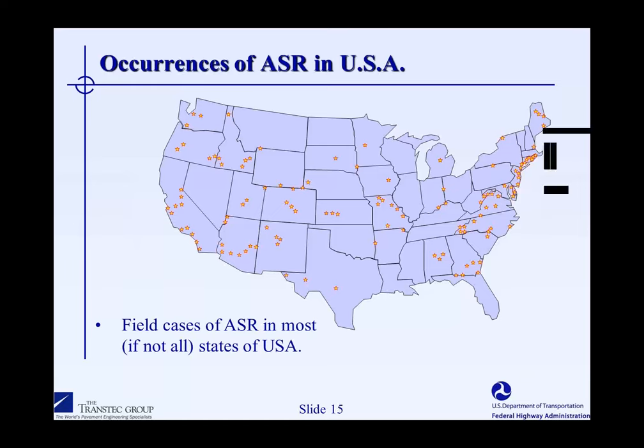This is a map that was produced around about 2000. It's already significantly out of date, but it shows you how ASR had spread by 2000. And you can see by this map that pretty much every state in the United States, at least the contiguous states, have had some problems with ASR. Every star on this map doesn't just represent a single case of ASR. It represents a geographic region where cases have occurred because of the geology of the aggregates.